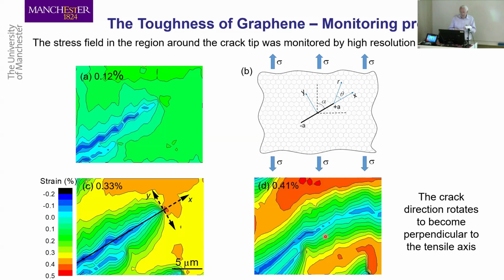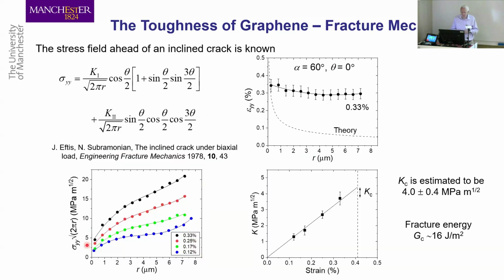So we also have these strain fields, and we know that stress is proportional to strain for this material. It's linear elastic. Therefore, we have stress fields, and we can work out the mechanics of what's going on. So there's just a little bit of mechanics here. We have to go to the textbook and find the stress field ahead of an inclined crack. We can go through the analysis of this. Ahead of the crack, we can look at the decay of stress, and we can then extrapolate back to the crack tip.